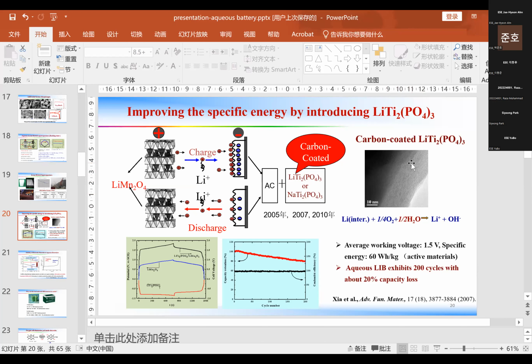The 001 plane is along this side, so lithium diffusion is kind of difficult. So we must control the defects, and also control the graphite. This prevents the oxygen from reacting with the lithiated lithium titanium phosphate. It is like a membrane, but not a porous one. It is only a crystal-defected membrane. This membrane allows lithium ion diffusion, but we prevent oxygen crossover.